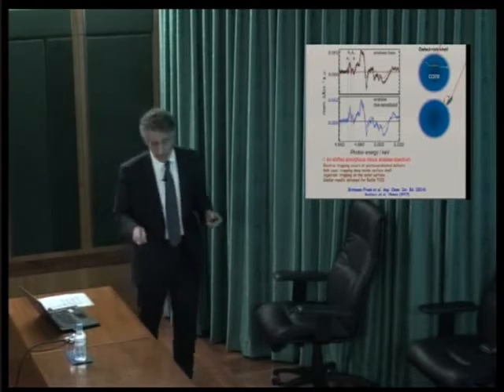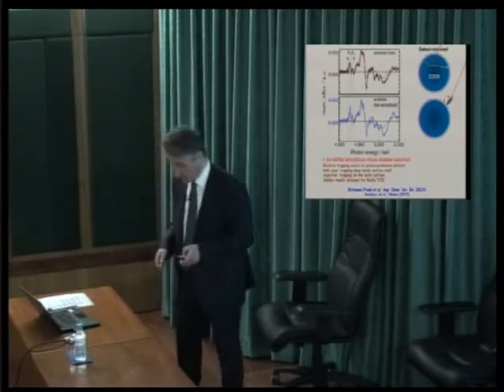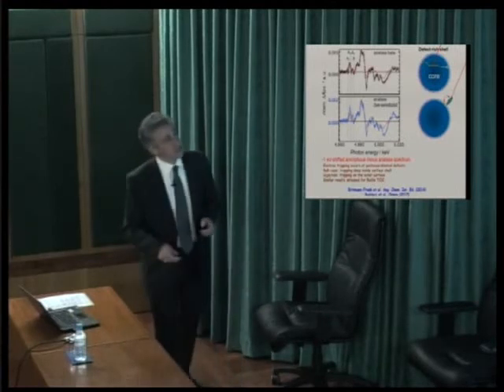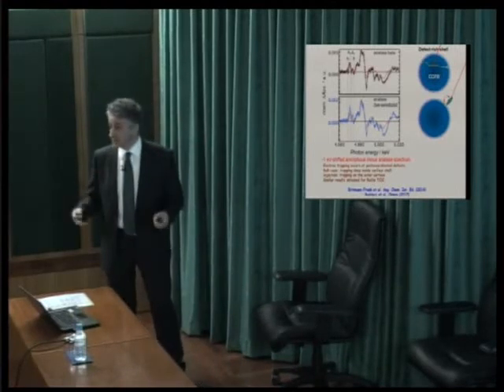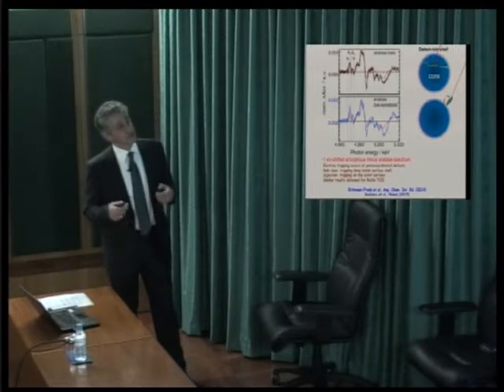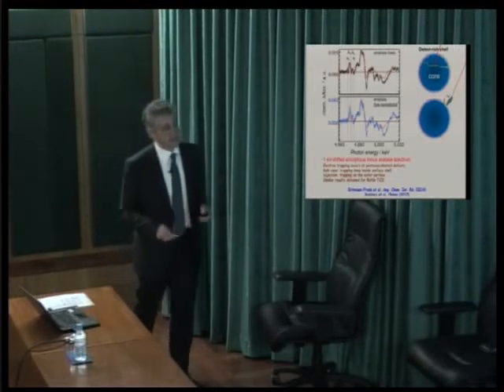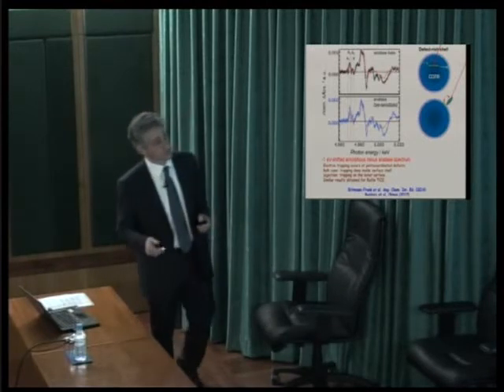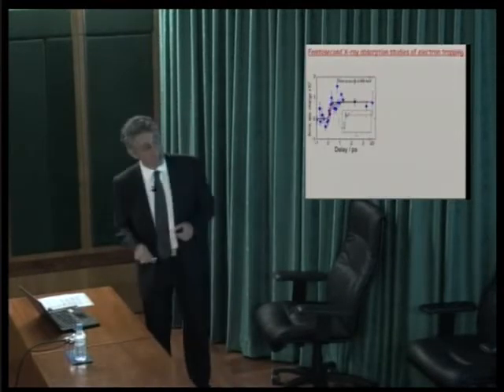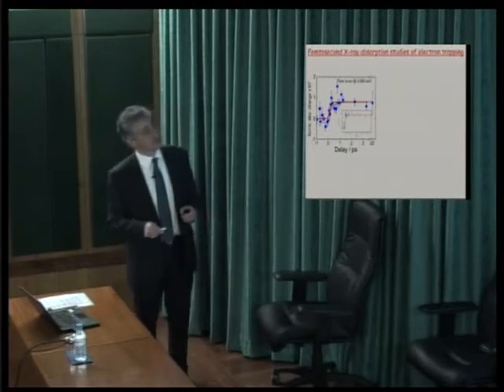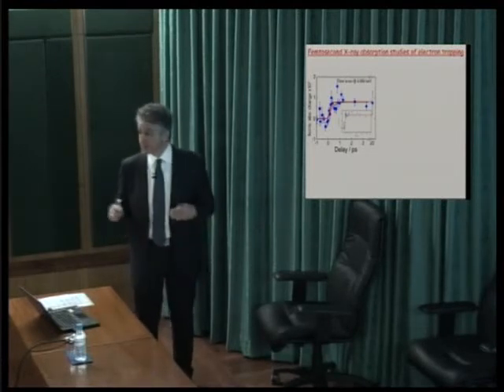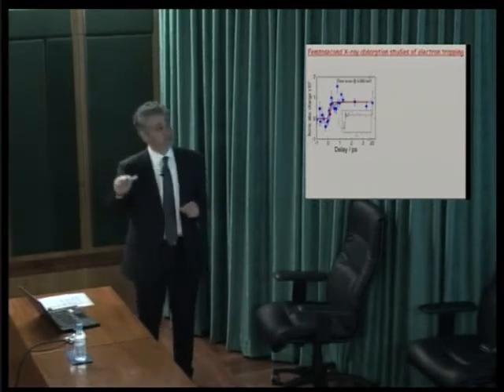And we also found similar results for other polymorphs of TiO2. So this was done with picosecond time resolution. It tells us what is the nature of the trapping sites, but it doesn't tell us how fast the trapping takes place. And we did probably the last experiment that was ever done on the slicing scheme. As I told you, this was done with 10 photons per pulse.